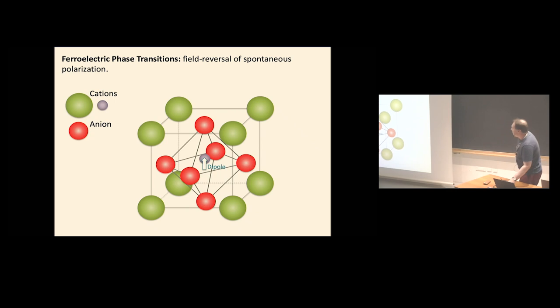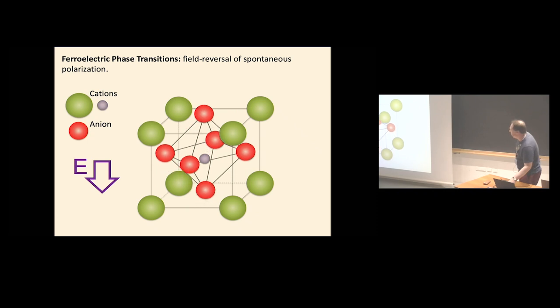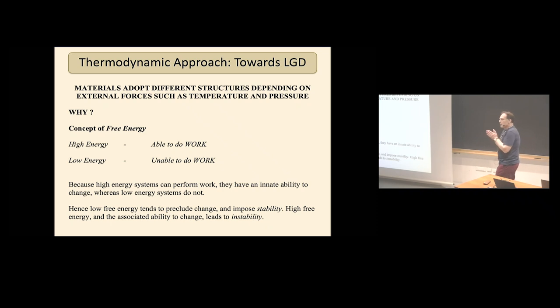Okay. There's one last thing, and that is that once you've developed this dipole moment in the unit cell, that's not enough for ferroelectricity. You must be able to reverse the sense of that polarization when you apply an electric field. So when you apply an electric field, that relative shift in the sublattices has to be reversible. Okay, but once you do those things, you have genuinely created a ferroelectric system. So that's what a ferroelectric is. That's what a phase transition in a ferroelectric is, and we're particularly focusing on the phase transition from an isotropic cubic into a non-isotropic tetragonal system in that example.